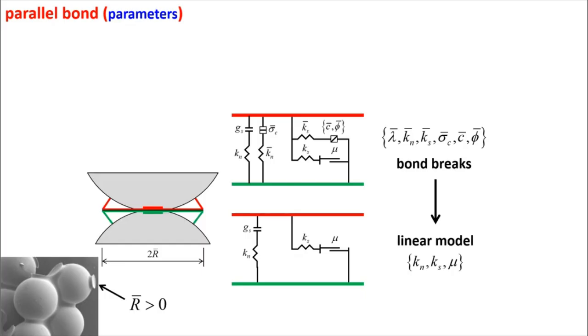So when you pull it apart, it might break at 10 MPa if it's a granite. And if you do a UCS on that same specimen, it's not going to break until 200 MPa. And so now you've got this ratio of UCS to tensile strength of 20. And if it's weakly cemented sandstone, that ratio is going to be like 3. And if it's super well cemented granite, that ratio might be as high as 32. The more well connected the rock is, the higher its UCS is, but it's still weak in tension, is what we find.